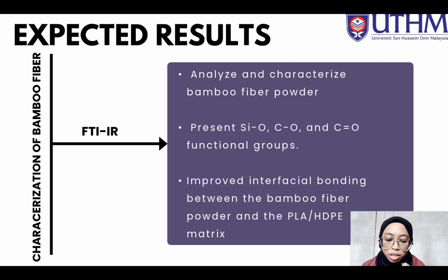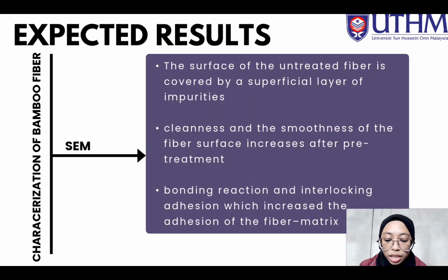So next, for the expected results. For FTIR, we use it to analyze and characterize bamboo fiber powder, to know the presence of the functional groups, and also to improve the interfacial bonding between the bamboo fiber powder and the PLA HDPE matrix. Next, the result of SEM.